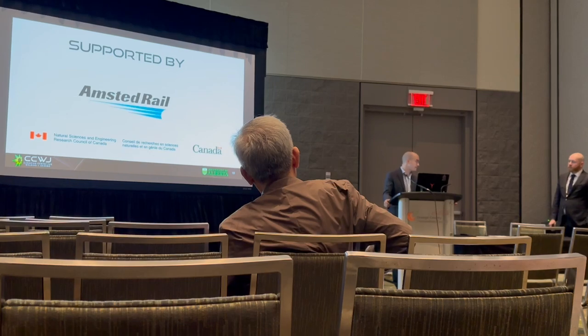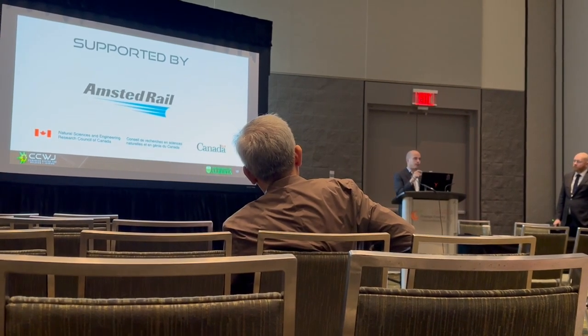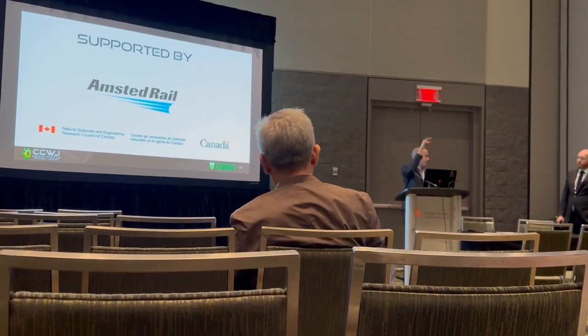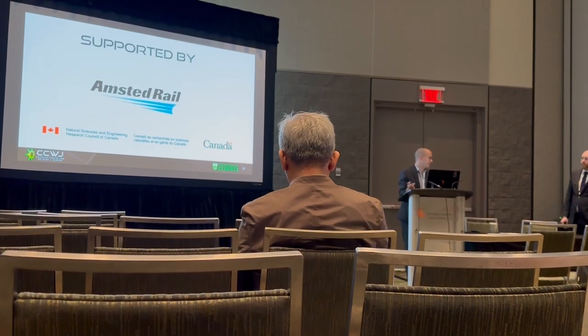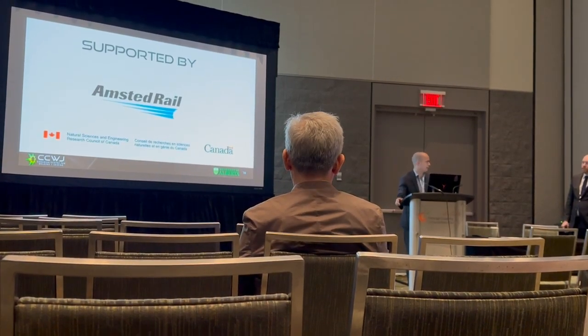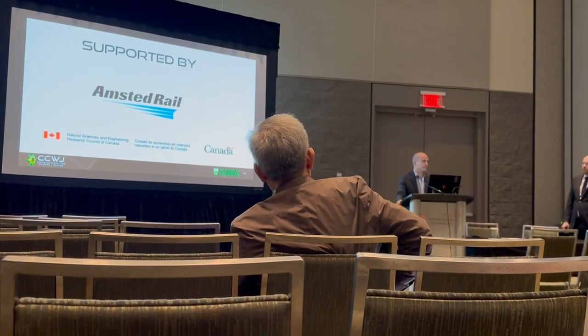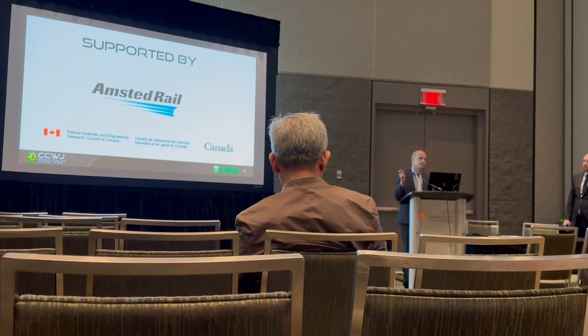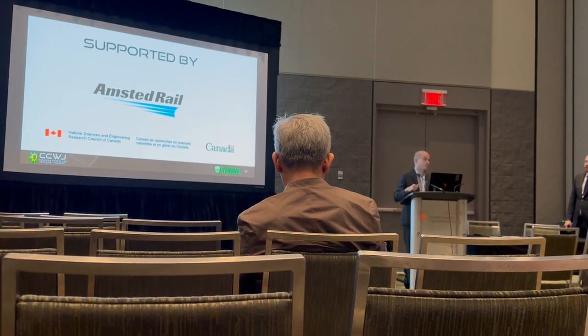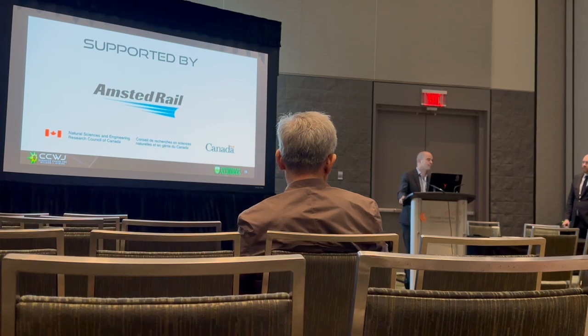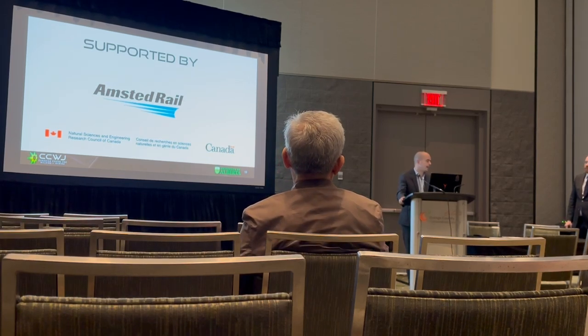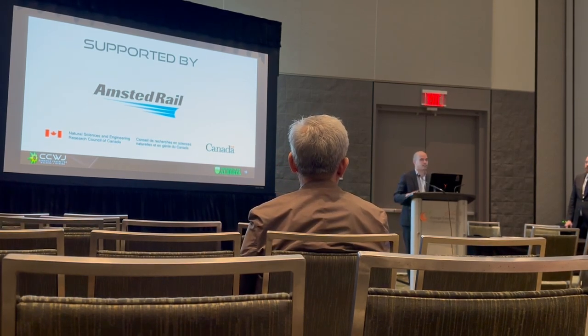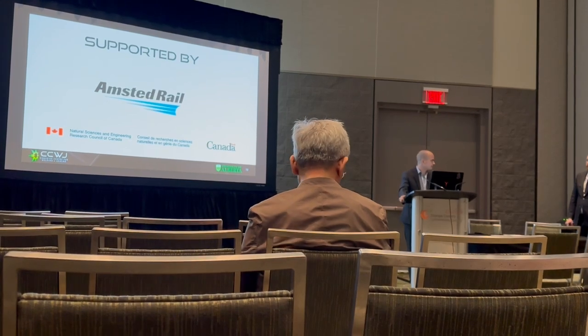In which case, if it does, you could end up hoping to see a compressive residual stress being set up through the whole depth. But obviously, some of it's going to be tempered, like become tempered martensite, and you're going to lose it. Like I said, the goal here in some ways was maybe you get compressive residual stress, maybe it just lets me weld on something that would have otherwise cracked to pieces. So you don't necessarily need to retain a really high degree right to the end if all the welds stick and it can survive into a heat treatment.